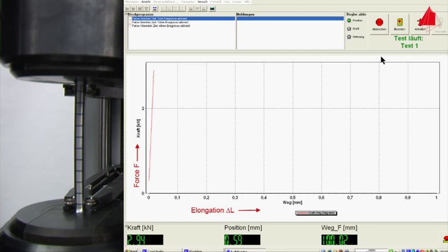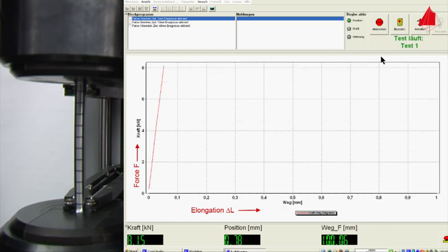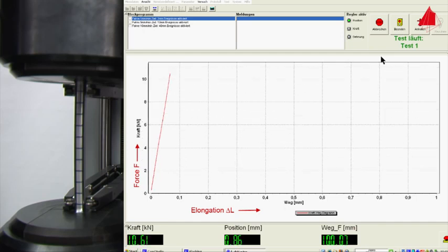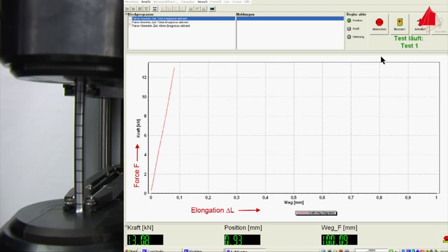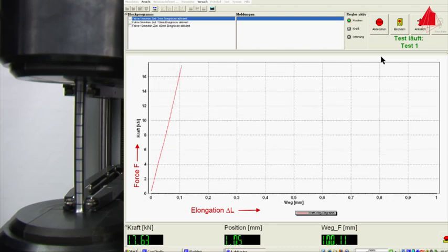At first the force rises rapidly. Force and elongation are proportional and form a steep straight line in the diagram. In this area, the material behaves elastically. If the test piece were to be unloaded from this area, it would spring back completely to its original length.